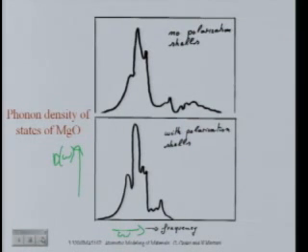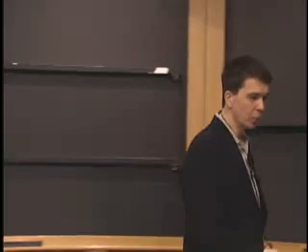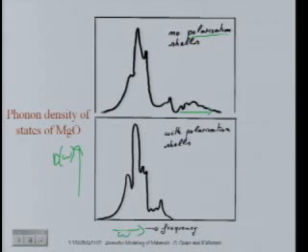And essentially what you see is that when you have no polarization, you have a high frequency tail of phonons. And remember, even though MgO is a highly symmetric crystal, the energy of phonons is determined by low symmetry things, because think of a displacement of a phonon, you're now breaking the translational symmetry. So you're not in the high symmetry 0 Kelvin crystalline environment anymore, so polarization becomes relevant. When you turn on polarization of the anions, you essentially dampen away those high frequencies.